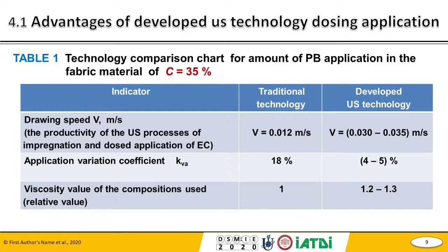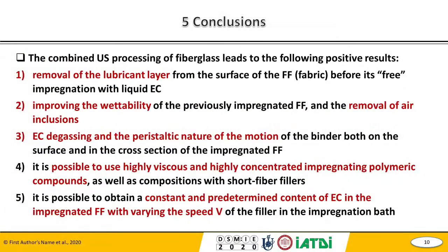So it is decreased by 4 to 5 times, and we can use polymer composition with viscosity higher by 20 to 30%. Please, next slide. In conclusion, we can state that our technology leads to the following positive results: removal of the lubricant layer from the surface before pre-impregnation with liquid epoxy compositions, and simultaneously improved wettability of impregnated fiber filaments. The next important result is removal of air inclusions from the structure of fiber filaments.